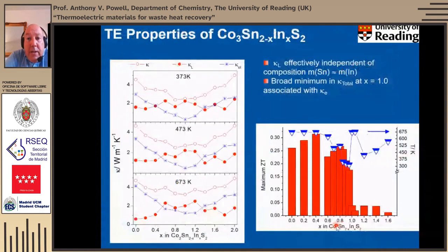Our thermal conductivity doesn't really change very much in terms of the lattice contribution, and that's not surprising because the mass of tin and indium are almost the same. They're right next to each other in the periodic table, but we do get a broad minimum in the thermal conductivity as we approach that 50-50 mixture. The 50-50 is at the lowest point here. We get a broad minimum due to the fact that the electronic contribution shows a minimum at that point because, of course, that's where the resistivity is highest.